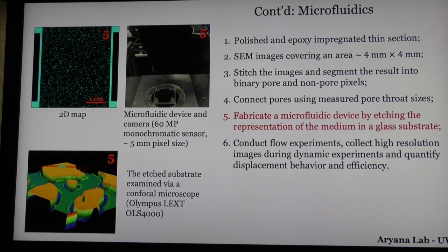And one more question. I don't know what the temperatures are at the subsurface region that you would be injecting into. So do you do your experiments at comparable temperatures, or are they all room temperature experiments? We do both. We have control over the temperature. Sometimes when we think temperature isn't a factor, based on our experience and published work, we say, let's just do room temperature so we don't have to worry about it. But sometimes we worry about temperature. Nanoparticle foam systems are sensitive to temperature, and over 100 degrees Celsius they start breaking down a lot faster. So that's something we try to establish.